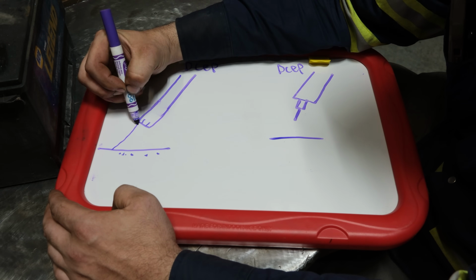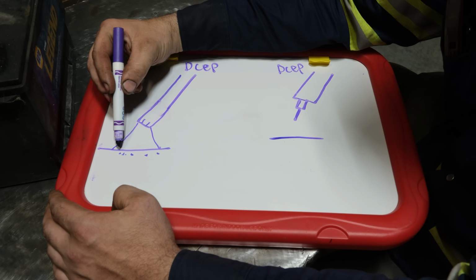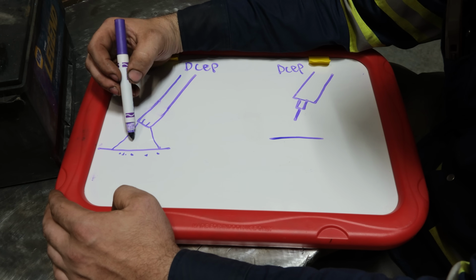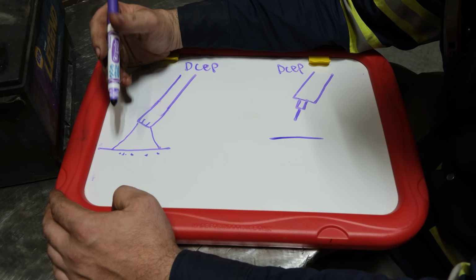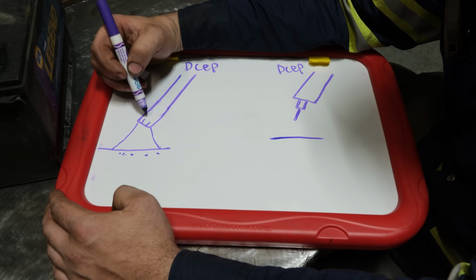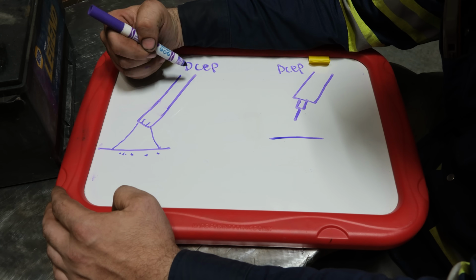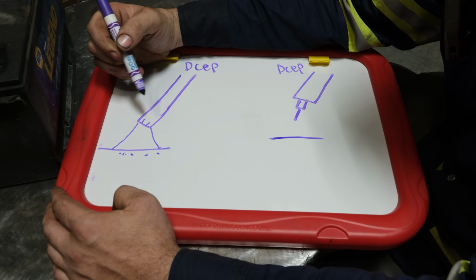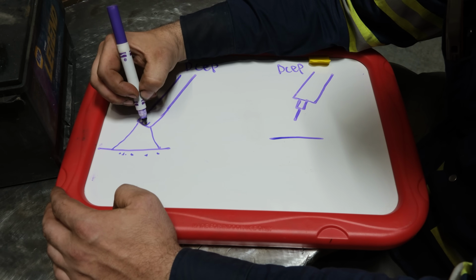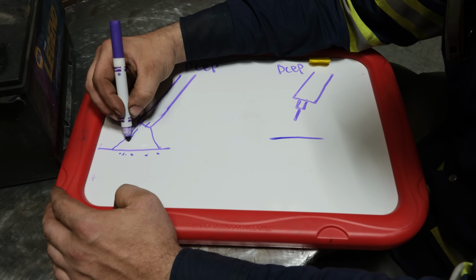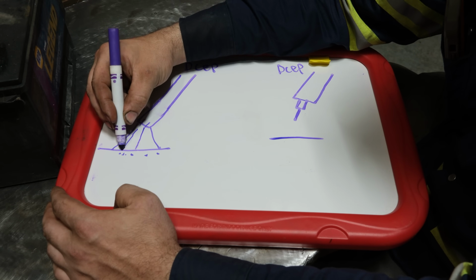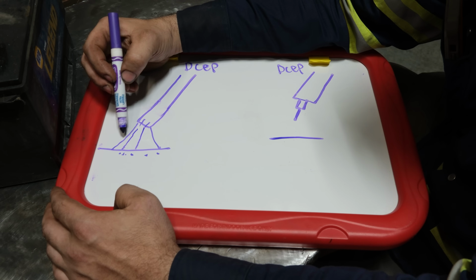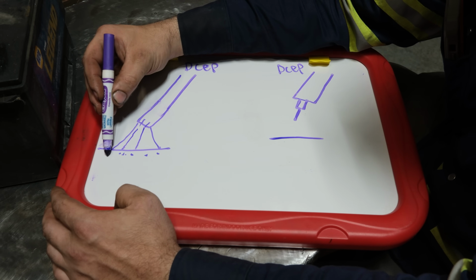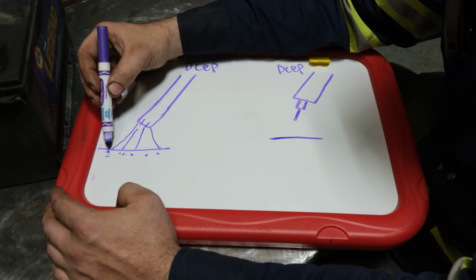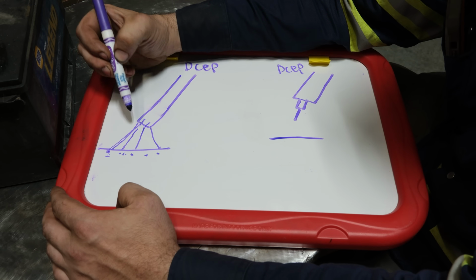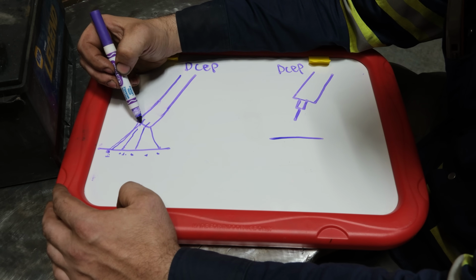Now with EP, you produce a wider arc cone. It is not as focused as on EN. To a certain extent, arc blow with stick is a bigger issue because you're running electrode positive. If you were to run electrode negative, you would have a much narrower arc cone, and it would be less likely to get arc blow, because arc blow, say an electron or a bunch of them over here wanted to jump over here, and it could, and they decided to, well, guess what?